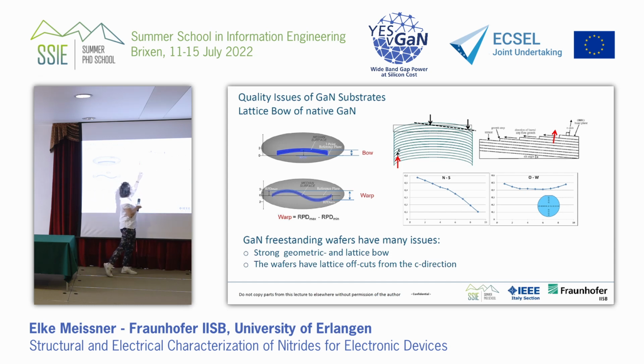And you see, for example, that if you measure such a wafer along the north-south direction, you have offcuts for one type of wafer. Of course, there are other suppliers, but this is one example, where you have offcuts between very close to 0 and 0.6 degree, which is quite a span, if you consider this from point of view of epitaxial conditions. And in the east to west direction, it's different. It's nearly no offcut. So it means that it's not even central. The wafer is like this. And this is all something which is not good for epitaxy later, and the quality of the epitaxy, we have heard, determines how good the device is.